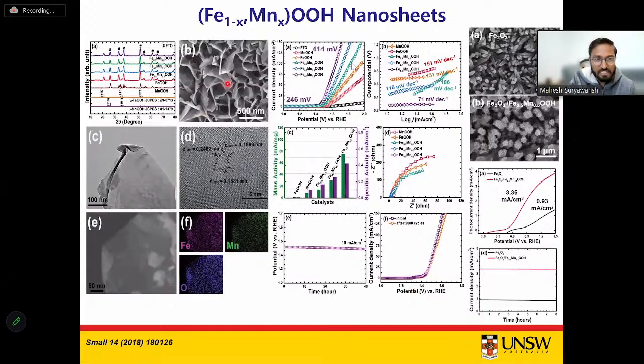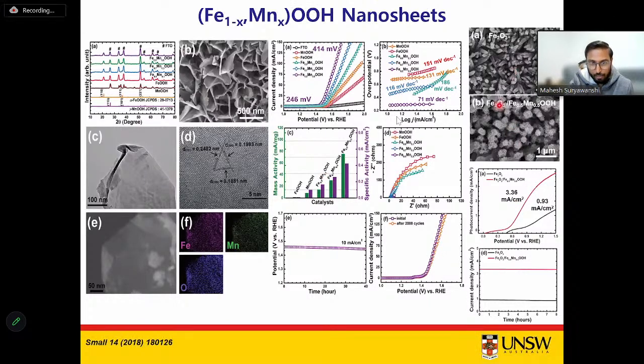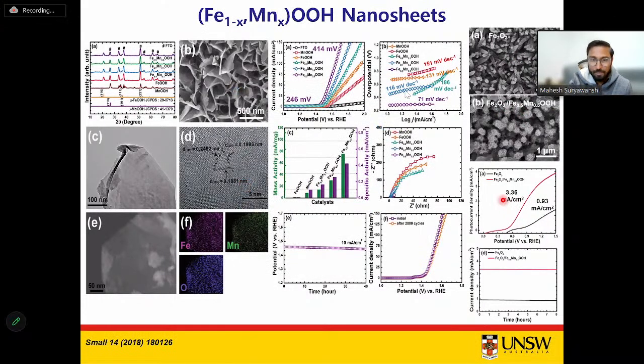So in the SEM images, you can see nice formation of nanosheets on an FTO substrate. But when you grow them on Fe2O3 nanorods, you can see there is a core shell formation of the nanosheets and the nanorod underneath. So the point is, when you test these photoelectrodes or photoanode in the water splitting reaction, you can see this bare Fe2O3 gives a current density of about 0.93 milliampere. But when you put this catalyst on the top of it, it improves the current density to almost 3.4 milliampere per centimeter square, which is kind of a huge improvement.